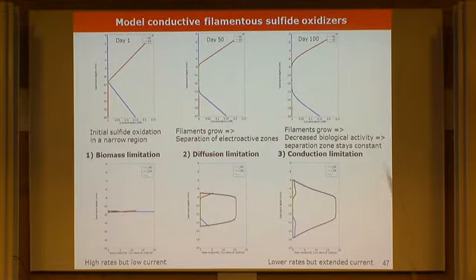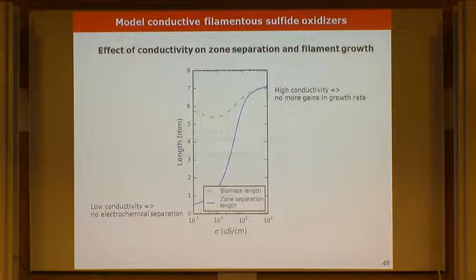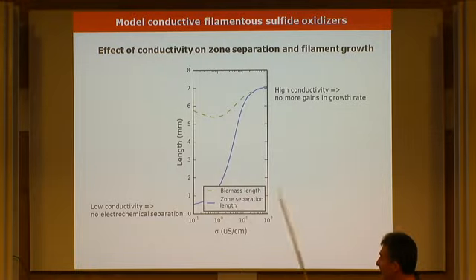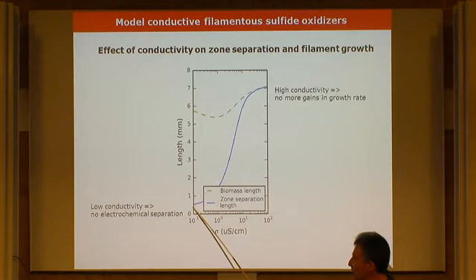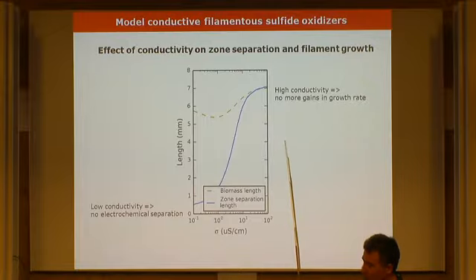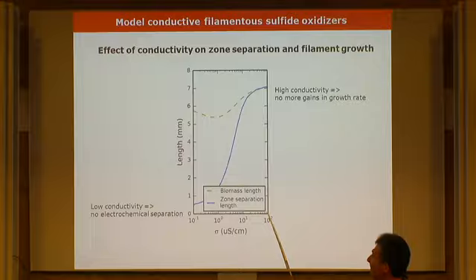And then you end up with conduction limitation. If the filament is too long, the resistance is too much. And actually, there seems to be an optimal filament length and also an optimal conductivity for this. So if the filament is not conductive, then you don't have this separation of zones, just normal SOBs. If the filament is too conductive, there is no gain anymore, because you really need to have this difference in potential developing between the two ends of the filament.